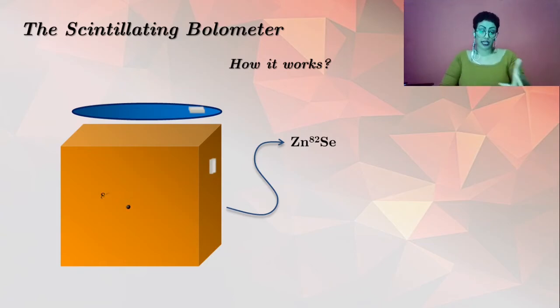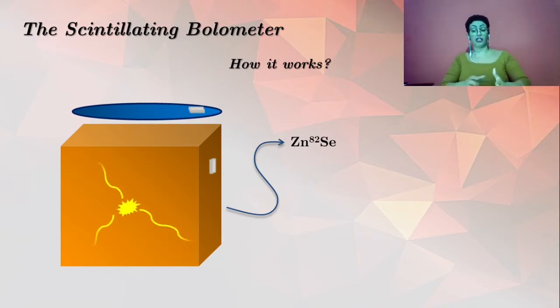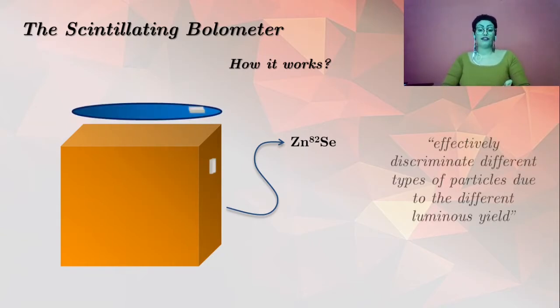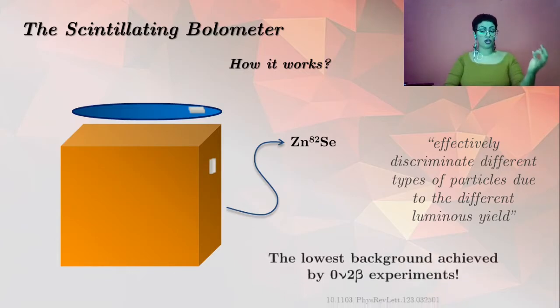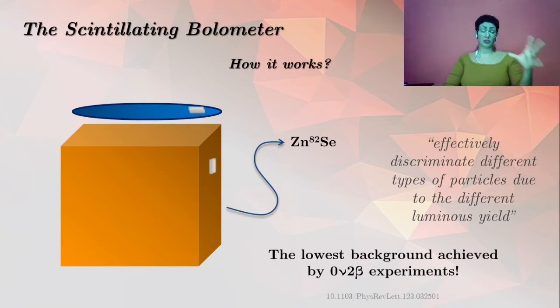If the selenium isotope decays, an amount of energy will be released that will raise the temperature of the material, and this thermal pulse will be detected by the thermistors. Also, as the zinc selenide is a scintillating luminescent material, part of the released energy of the decay will be converted into a light signal that will be detected by the light detector. This combined result allows us to effectively discriminate different types of particles due to the different light yields that each interaction induces in the material, leading to a drastic reduction of the detection background level of the experiment.